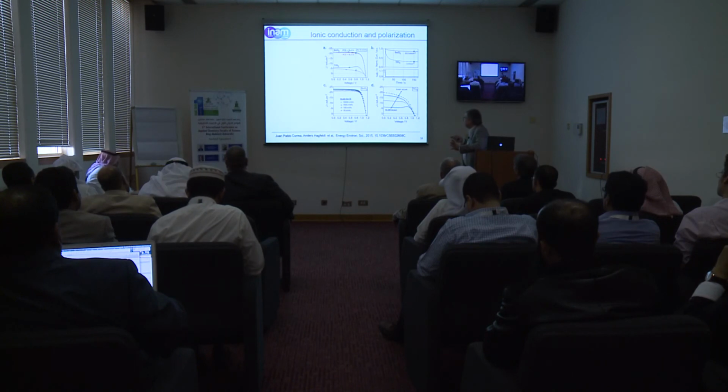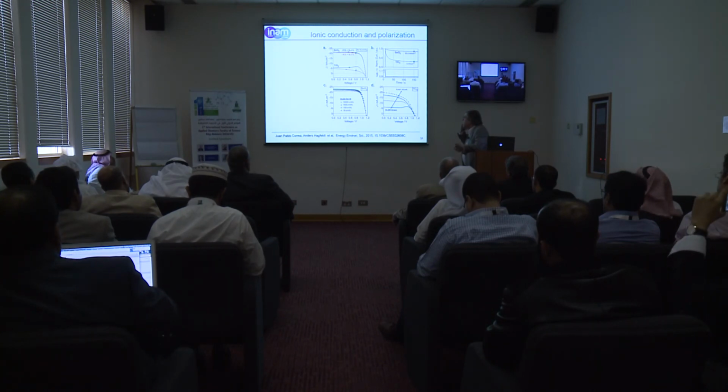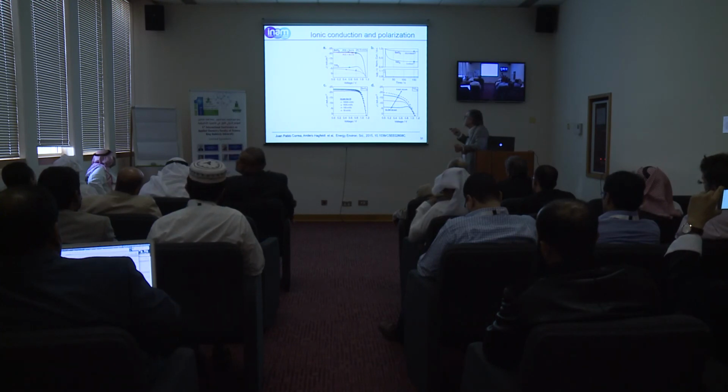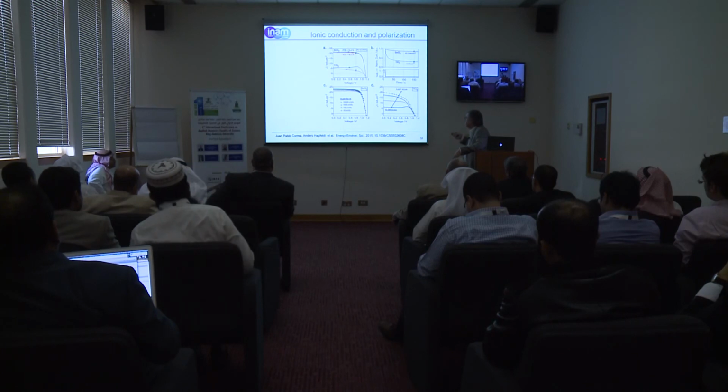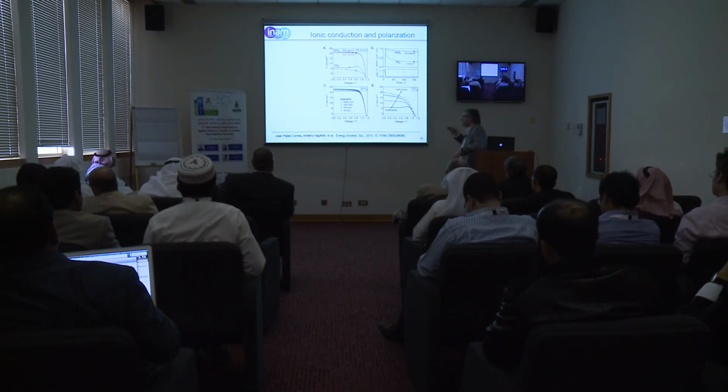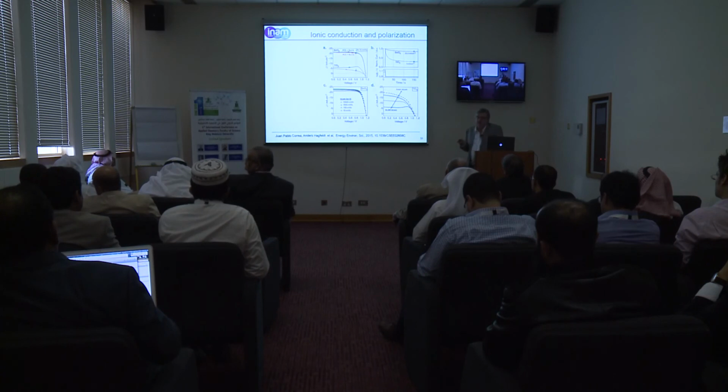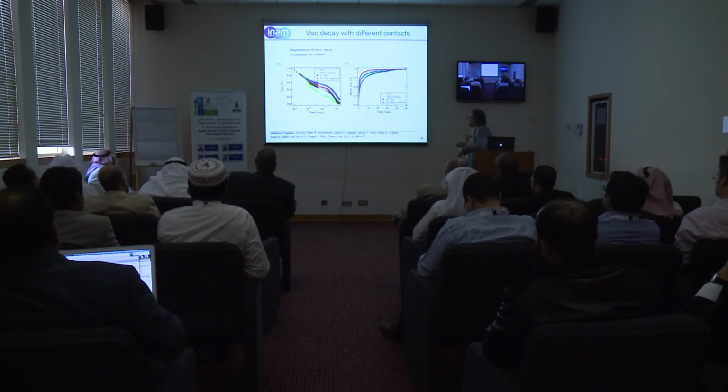These are very drastic changes shown by the work of Hagfeldt and all the people in EPFL, already discussed this morning also by Dr. Nasser, showing very big hysteresis when the TiO2 is made by atomic layer deposition. Here is the hysteresis, in addition to the bad injection of this atomic layer deposition TiO2, which is really bad with respect to the spray pyrolysis. And this is VOC decay.